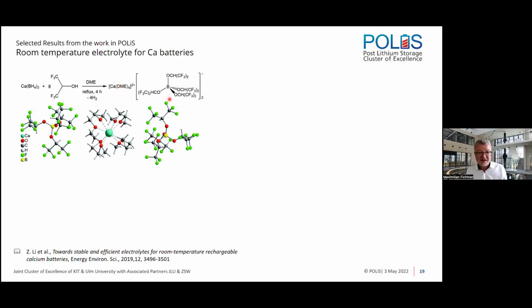Yeah, so this is the calcium salt. The borohydride reacts with the acidic proton of the isopropanol. And the only byproduct is hydrogen, which goes off. So you get basically full conversion to the product. You don't need to make complicated intermediate steps. You make the reaction, and then you get this electrolyte.